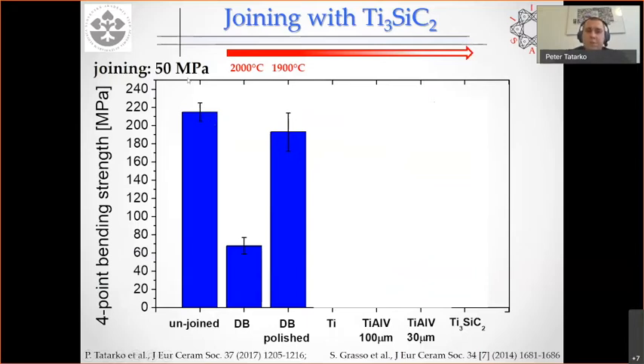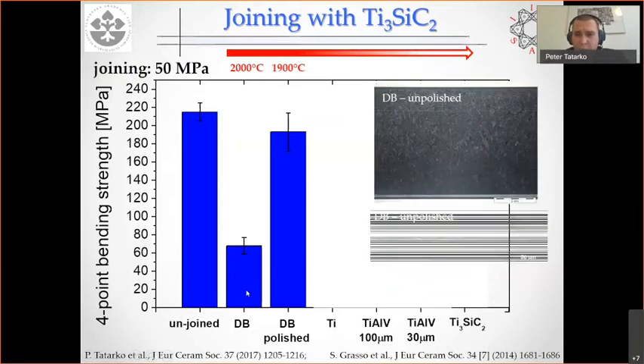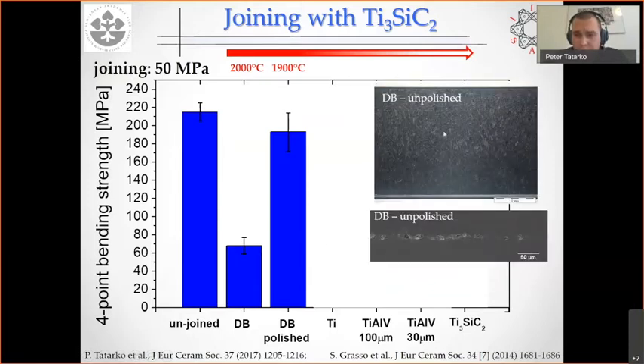And you can see for joining, we used 50 megapascals and 2000 degrees in this case, and 1900 in the second case. Especially, we got very poor bending strength performance for this unpolished sample. The reason was very simple. If you look here on the tensile surface, you can see the joint. And if you look closer at a higher magnification, you can see these voids at the interfaces. It's logical, because you don't have the polished surface, so you have a very high surface roughness. So even though we used 2000 degrees C, the joining conditions were not enough to allow solid state diffusion and to fill up these voids.